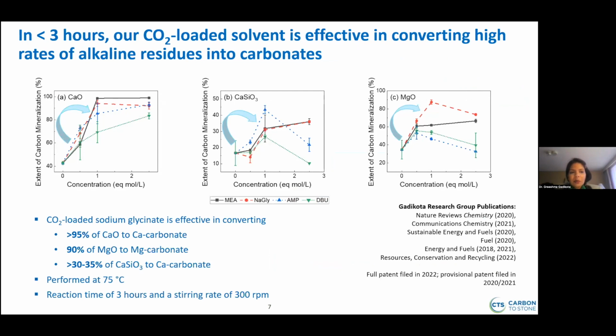So if we have calcium oxide, we're able to mineralize close to 100% of that in less than 3 hours using a wide range of different solvents. So here we've looked at monoethanolamine, which is represented by this black line. Sodium glycinate also works really well. We also have more complex amines like AMP and DBU, though these are known as tertiary amines or cyclic amines, respectively.